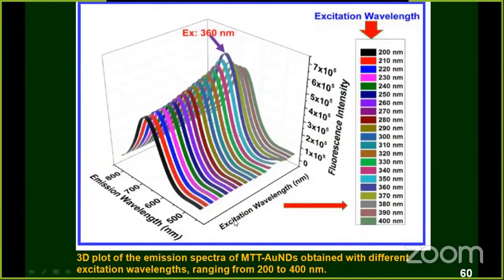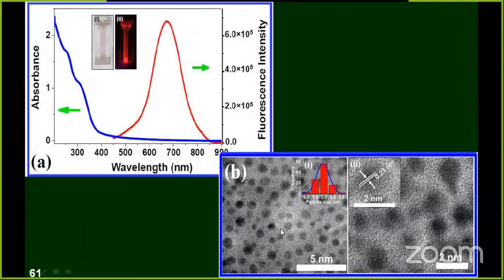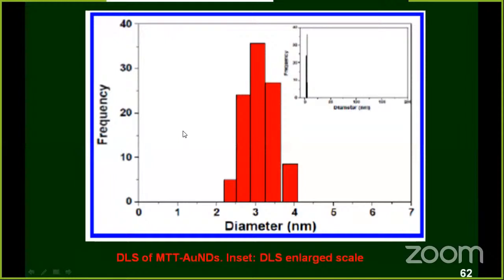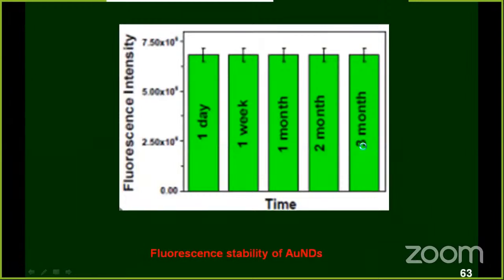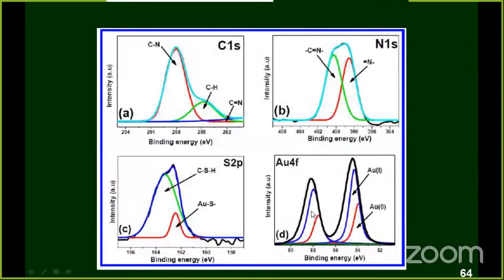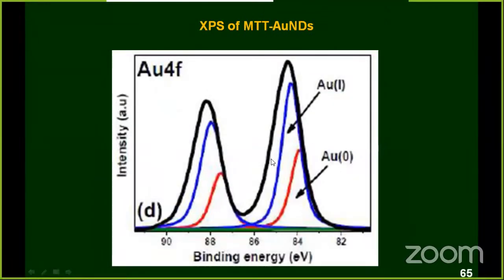This one is higher, this is the excitation, this is the fluorescence, this is the emission wavelength. We did this using very simple free software only. And these are the particle size, again it is 2 nanometers, and this is the red emission. The particle size, see here, is around 3 nanometers. And it is also stable for 3 months. And this XPS peak, as I mentioned earlier, is Au0 and Au1. The middle core, central core is Au0, then the outer core is Au1. Au1 will not be as Au1, it is a complex. Au-S, it's a complex. So how much Au1 is there, that much fluorescence you can get. Here, 60% we got. So high fluorescence we got here.